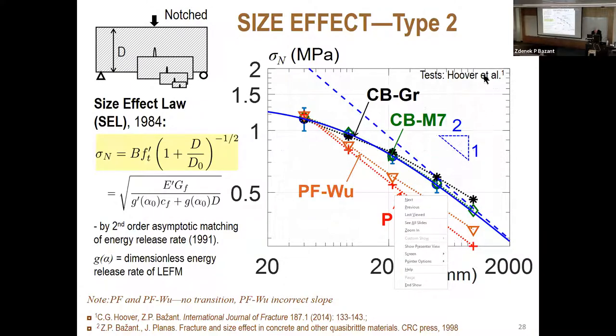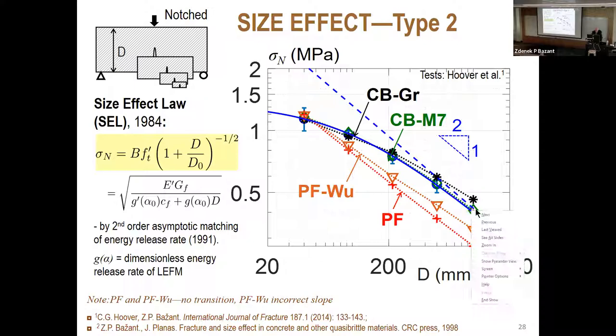They are from recent tests by Hoover and Northwestern, which has a big range and small scatter. And you see that CB-M7 and Grassel both match very well. Grassel is the black, the green is the M7 model. However, the models by phase field model and modified by Wu don't match well. In fact, they seem to give power law, but power law not exponent 1/2.